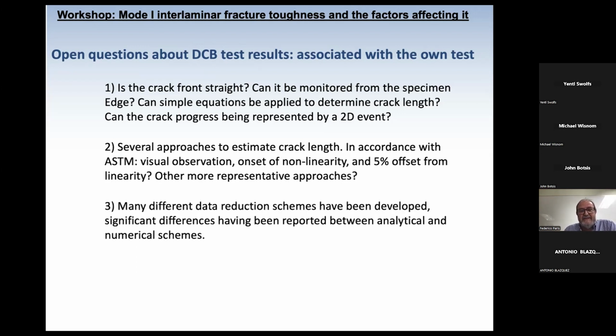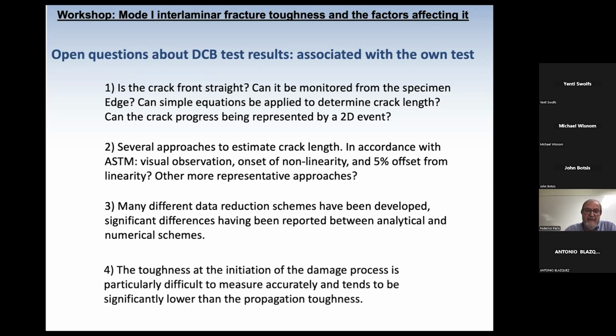Additionally, many different data reduction schemes have been developed, and significant differences have been reported between analytical and numerical schemes to be used in the data reduction procedure. The toughness at the initiation of the damage process is particularly difficult to measure accurately and tends to be significantly lower than the propagation toughness. Don't worry if you don't agree with this. I know people that have found exactly the opposite. I'm just putting questions on the table to try to be answered during our workshop.